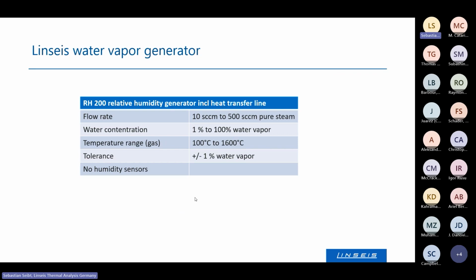Some specs: the flow rate of our humidity generator goes from 10 standard cubic centimeters per minute up to 500 for pure steam, so a bit lower rates than for the humidity. We can run water vapor concentrations of 1 up to 100% in the system, for a temperature range between 100 centigrade, of course, up to 1600.